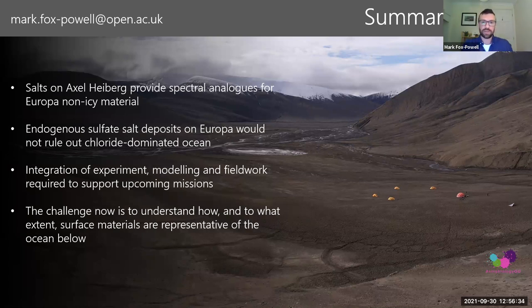That's kind of a tangent from your question, but that suggests that it's quite well mixed, which means that the pH that we're inferring from plume data, which is effectively the source region of the plumes, might be representative of the whole water column, at least at that part of Enceladus. I hope that helps to answer.